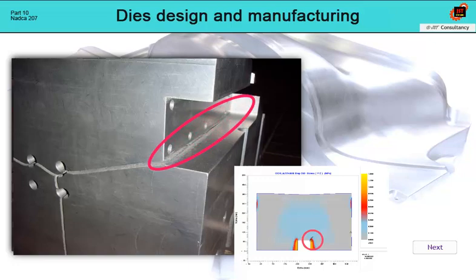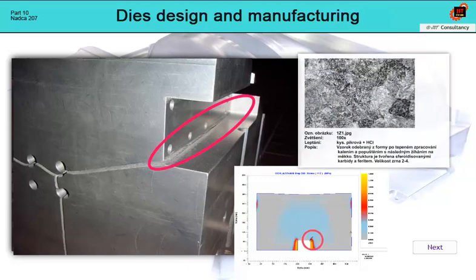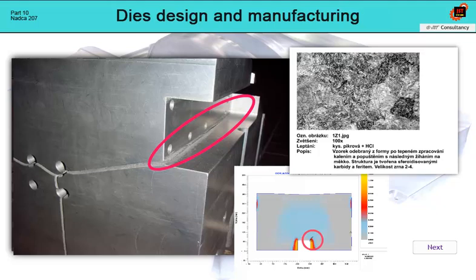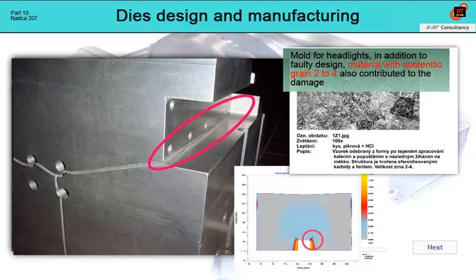The quality of the material also contributes to the spread of the crack. When after a metallographic examination it was found that grain size 2 to 4 does not correspond to the specification, for example, grain size 7. Despite the fact that it is a massive piece, the body cracked right up to the center of the insert.